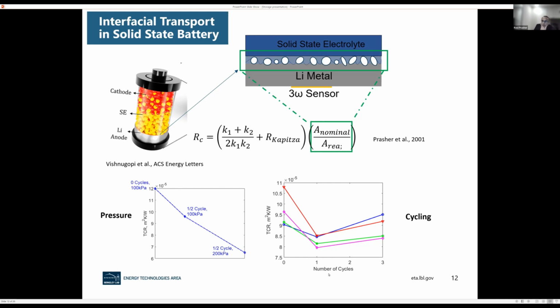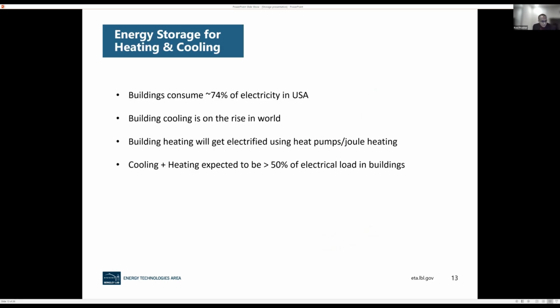We're seeing that this contact resistance changes with pressure. We're also seeing some very interesting behavior with cycling. So we are hoping that with this technique, we will be able to uncover a lot of electrochemical phenomena at that interface. And particularly, we will be able to calculate this actual A nominal and A real and feed that into the electrochemical models, right? All right, so moving on.